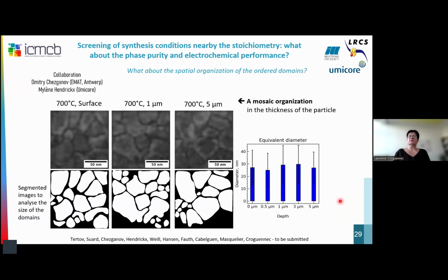If we look at these images here, we have from the surface to the bulk of our materials a mosaic organization in the thickness of the particles. And you can see that when we screen the particles, from the surface to the bulk, we have the same average equivalent diameter size for these domains.